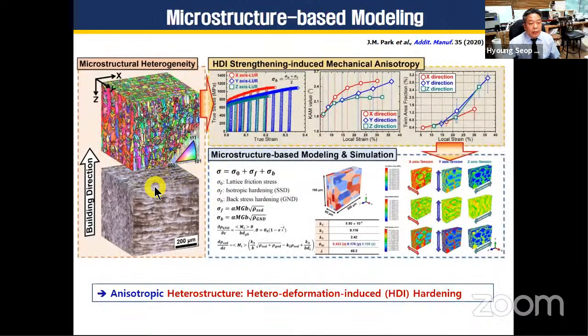The microstructure and HDI strengthening mechanism based constitutive model, considering GND, geometrically necessary dislocation, as the source of back stress and HDI strengthening, and this is for forward strengthening, as well as the SSD, was developed. And this model was implemented into the finite element modeling. There's very clear anisotropic behavior experimentally and in simulation as well, and it could be reproduced by the finite element simulation and analyzed. This X direction and Y direction and Z, this building direction properties are very different. It shows very anisotropic behavior.